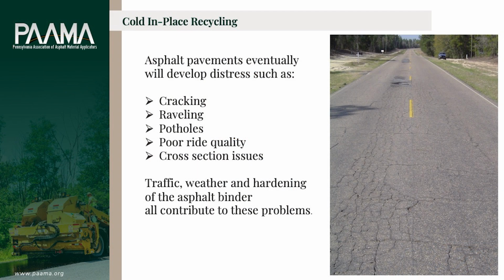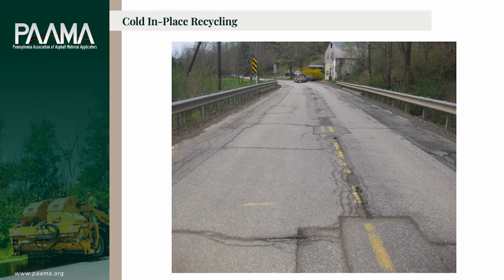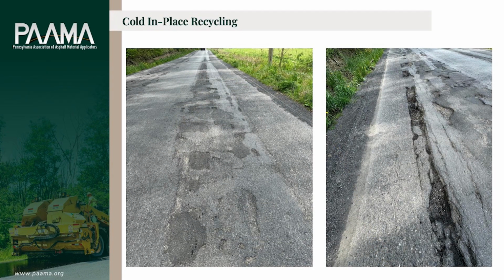So what the asphalt pavements eventually develop, as you know, are cracks, raveling, potholes, poor ride, cross sections. The roadways are getting cold in the wintertime and very hot in the summertime. So you're going to have all kinds of cracking going on, potholes. This is a typical type of roadway that we would recycle, patch on top of patch. Here's a good roadway for recycling. You see the center has gone already, so the joint at the center is broken apart.